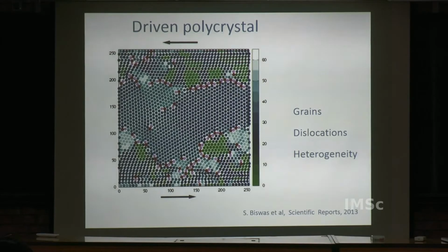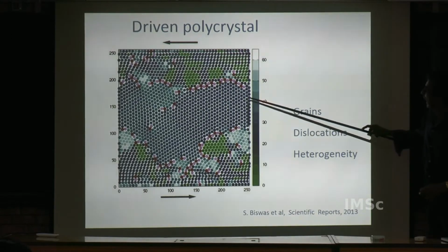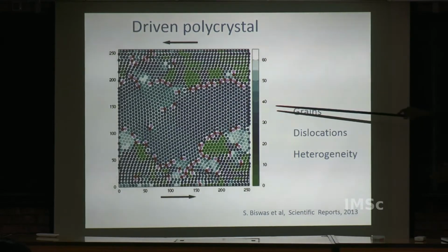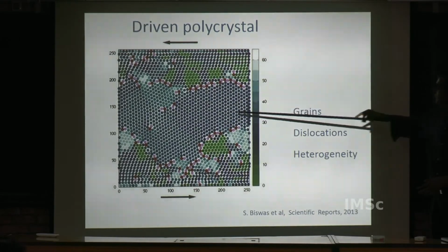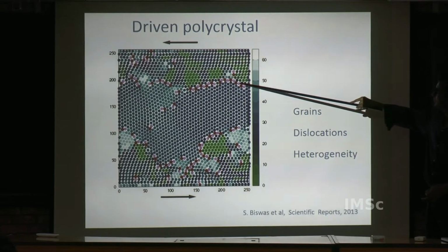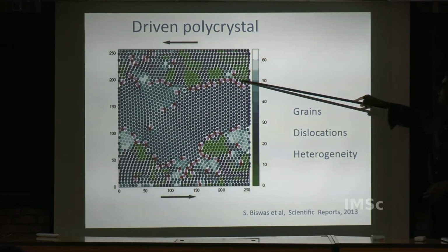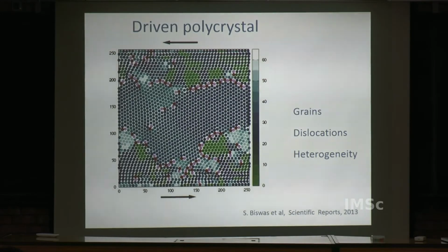So this is a typical state. Here you can see these hexagonal arrangements. Remember that these particles are nothing but peaks in your density field. Inside, it looks perfectly ordered, with 6-fold symmetry, whereas at the boundaries you see this pink and red. They are basically 7-fold and 5-fold coordination numbers, and they always come in pairs.